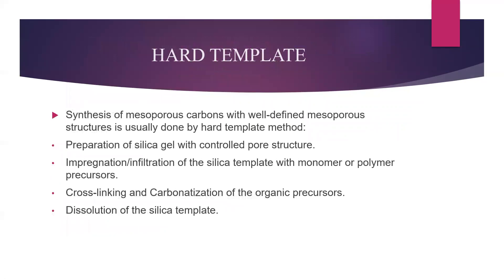Synthesis of mesoporous carbons with well-defined mesopore structures is usually done by the hard template method. The steps include: preparation of silica gel with controlled pore structure, impregnation or infiltration of the silica template with monomer or polymer precursors, cross-linking and carbonization of the organic precursors, and dissolution of the silica template.